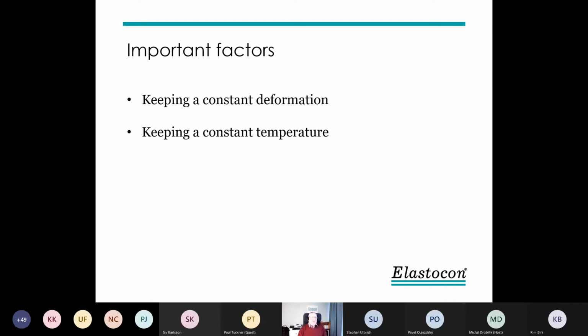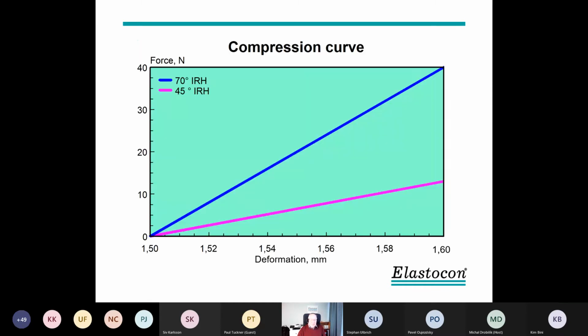We found that there are some factors which are very important. That is keeping a very constant deformation and keeping a constant temperature. Here is a curve. The standard test piece is 6 to 6.3 millimeters. So if we assume we have a 6 millimeter thick test piece, normally it's compressed to 25%. It means 1.5 millimeter. In this case, we have measured the force from a sample compressed at 1.5 millimeter and further increased the compression to 1.6 millimeter.